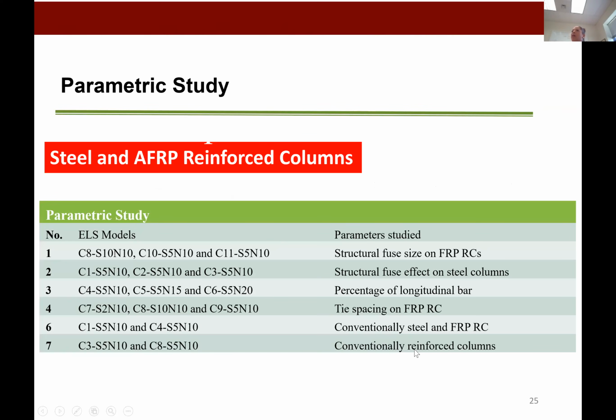So for the parametric study for this case, again, comparing the steel and the AFRP, we had several models, and I'll go through the nomenclature of how we selected these, but we looked at several models where the main parameters that we were looking at in terms of design was varying the size of the structural fuse, looking at the various structural fuse effect on the steel columns, also varying the percentage of the longitudinal bar ratio, of course looking at confinement, that is the tie spacing of the FRP bars within the reinforced column. Then the other cases, C1 and C4, are conventionally steel and FRP reinforced concrete, so we'll keep our eye on C4. And then the conventionally reinforced columns are C3 and C8.